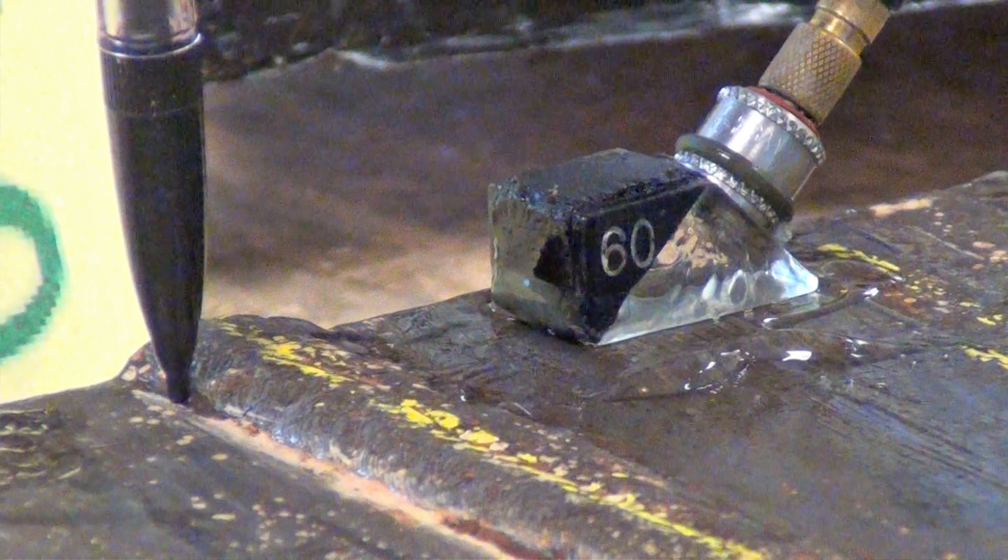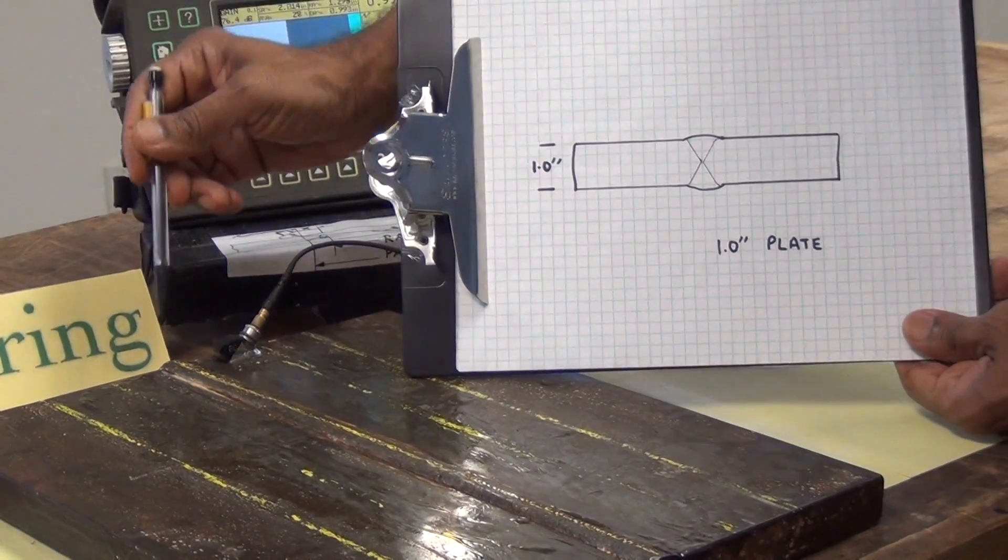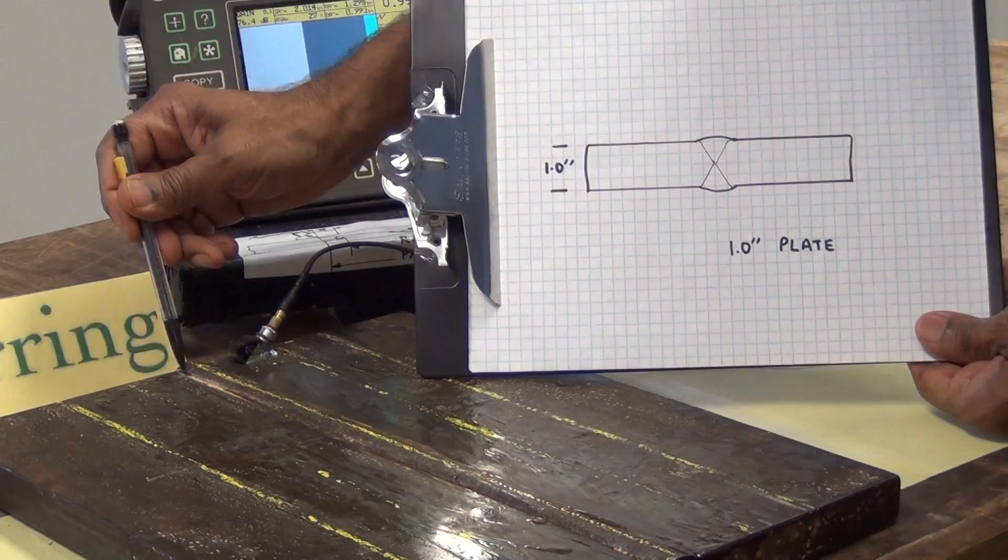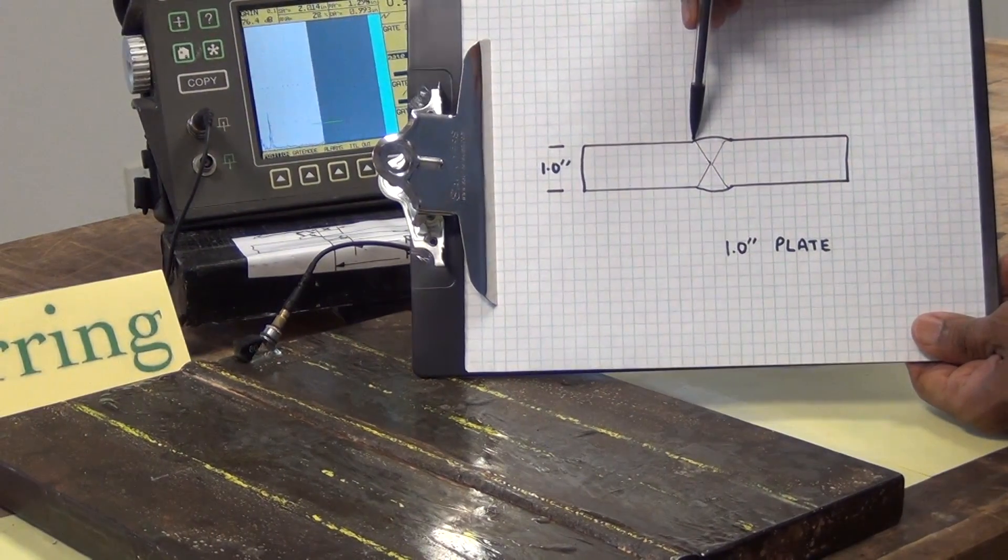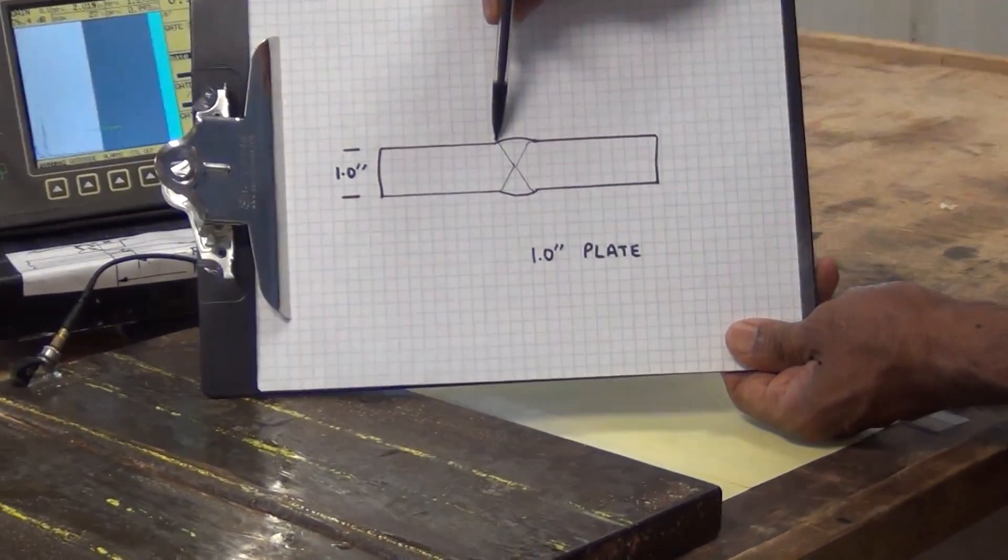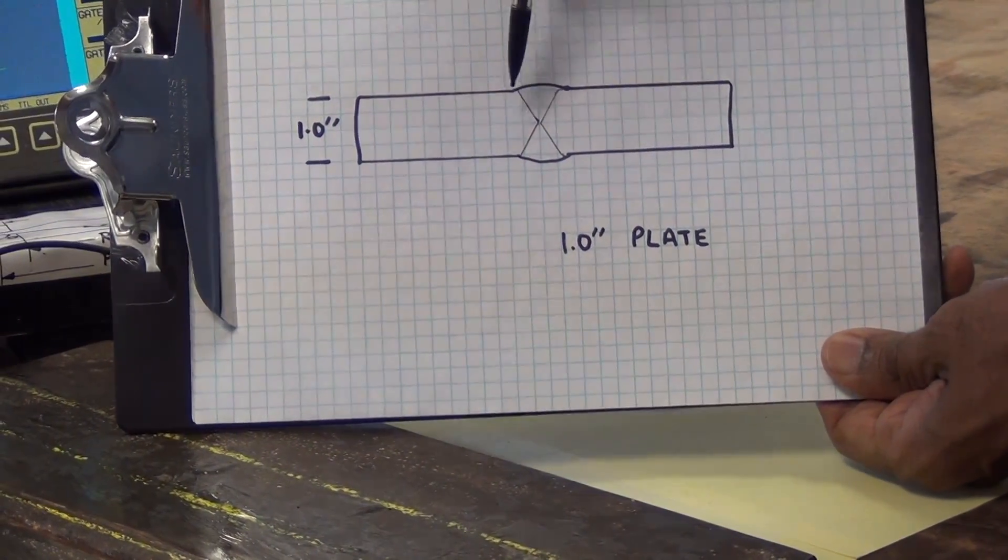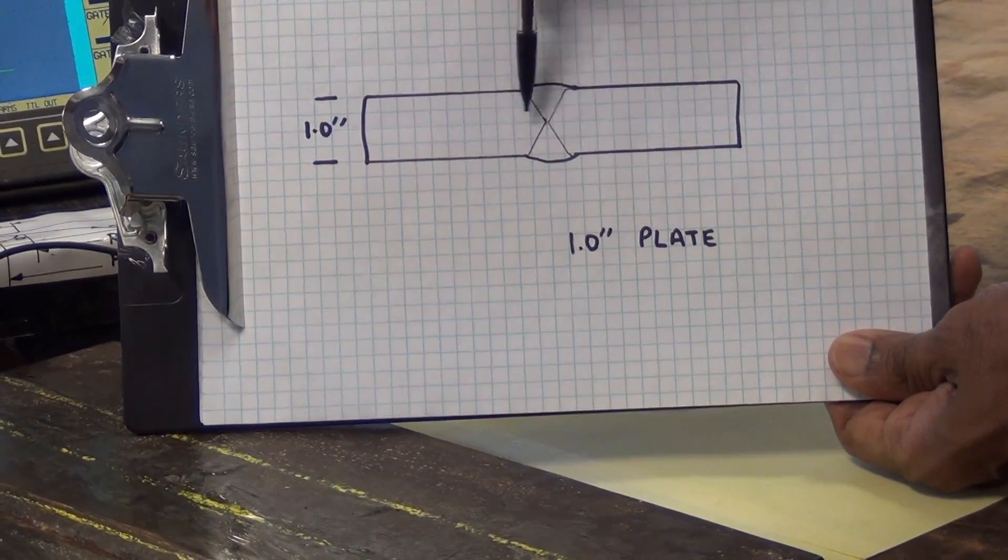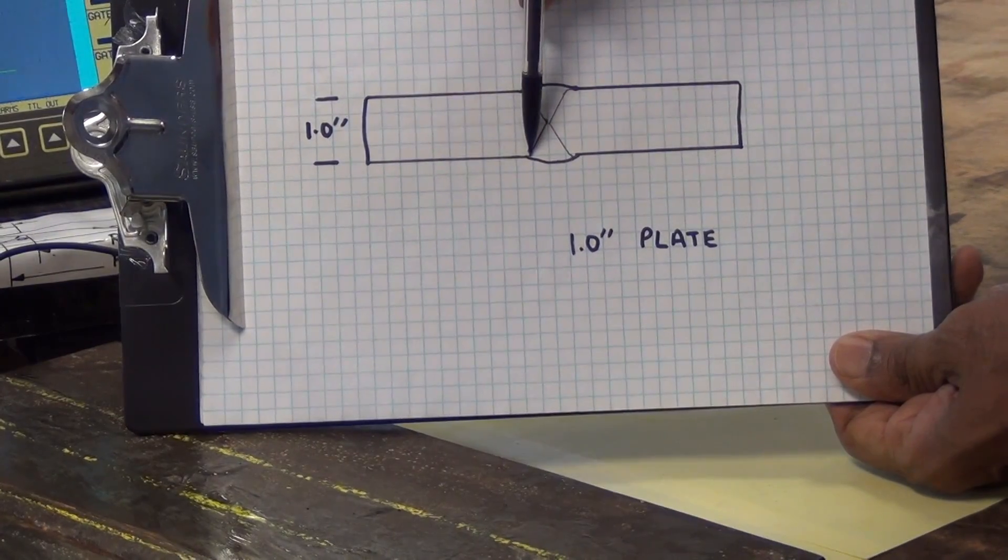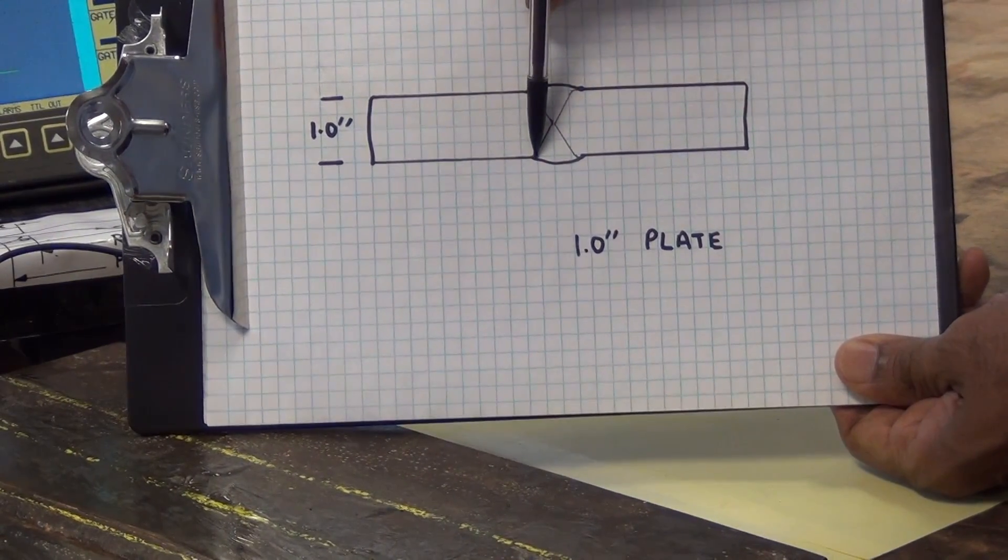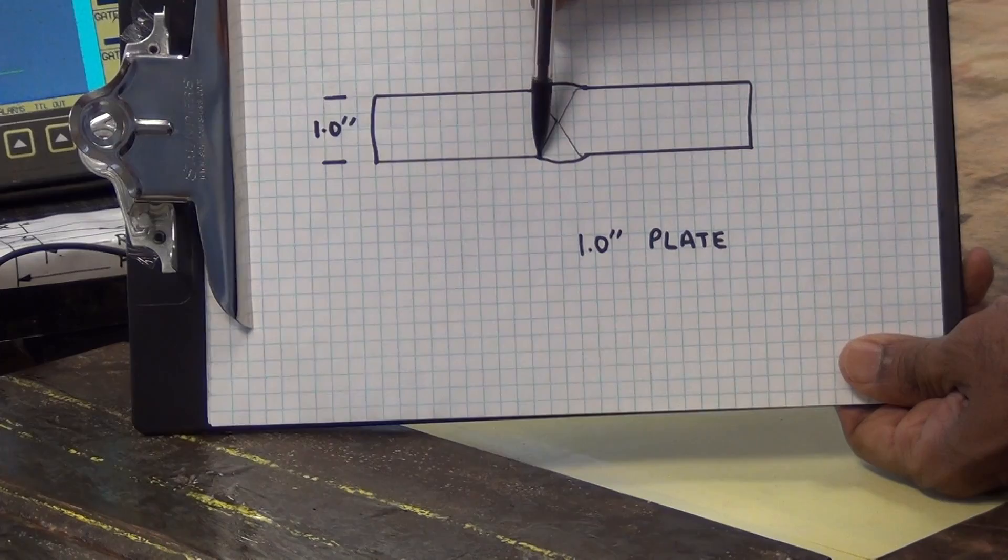Now let me go to the drawing of this plate and we will transfer this point from this plate to the drawing. So that point from the plate corresponds to this point on the drawing. And then from there, we have to go 0.993 inches down, which is basically 1 inch, and that would correspond to the point here on the weld. So that reflection is from the bottom cap of the weld.